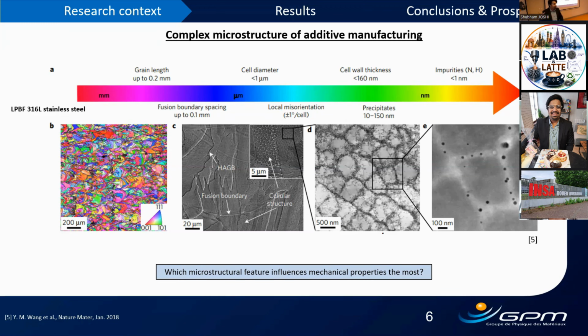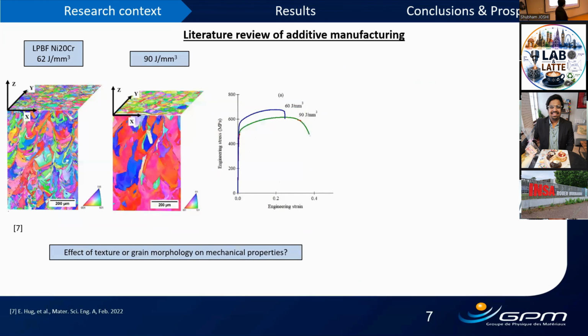So, having researched for more than a couple of decades now, researchers are still trying to find the answer to which of these multi-length scale microstructural features are responsible for mechanical properties. Talking about the highest lens scale, which we discussed, in a literature review of nickel 20 chromium fabricated with LPBF, we see that crystallographic texture and grain morphology could be associated with process parameters. So if we change process parameters, we can see the difference in texture, grain morphology, etc.